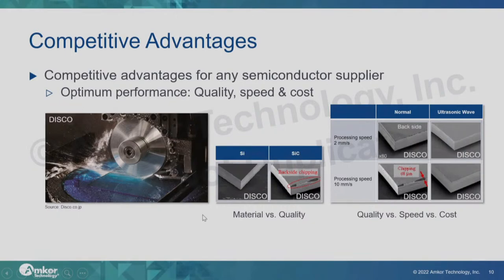For silicon, you can see in the picture in the middle, the cutting is very smooth and neat. But when we put in the silicon carbide, you can see backside chipping. The black color represents where some chipping happened, right? Then we can slow down the processing speed to, let's say, 2 mm per second, right? That is a tremendous reduction in speed from 50 mm per second to 2 mm per second. And it helped, but when we increase the speed to 10, you still see the issue.